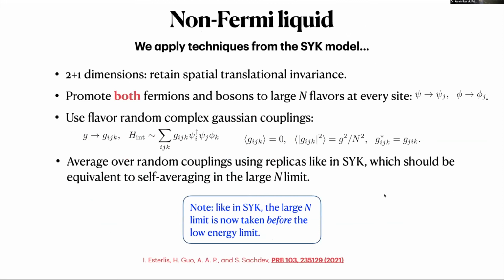To apply this to something that's beyond 0 dimensions is fairly straightforward. All that you have to do is keep the dispersions of the fermions and the bosons in your 2-dimensional theory, but promote both fermions and bosons to have large N flavors at every site. And then again, use the same kind of random coupling between fermions and bosons. In the large N limit, this gives you an exact set of RPA Schwinger-Dyson equations. And just like in SYK, even here we take the large N limit before the low energy limit in order to be able to solve the problem.